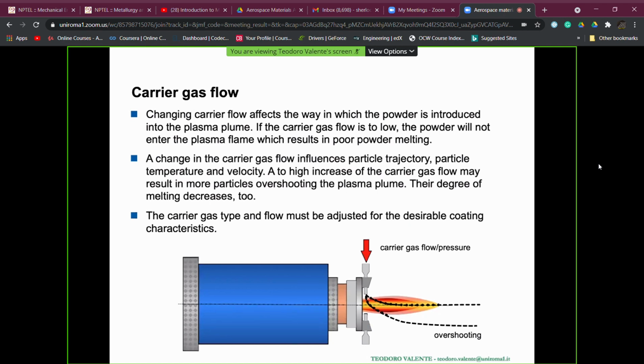it can affect the way in which the powder is introduced into the plasma plume. If the carrier gas flow is too low, the powder will not enter the plasma flame, and this results in poor powder melting. As well, if the carrier gas flow is too high, we can have a phenomenon which is called overshooting, like this. That is, particles can travel across, and again, they cannot experience a good melting behavior, giving rise, for example, to unmelted particles which can be incorporated into the coatings, or dust inside the spraying chamber.